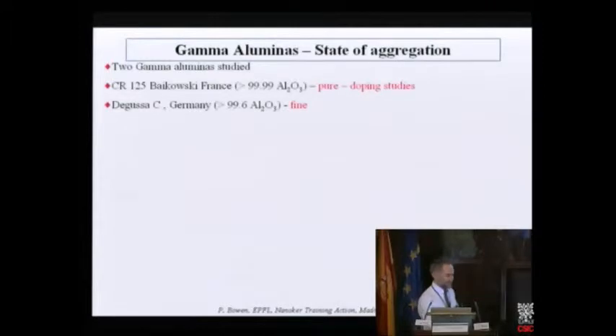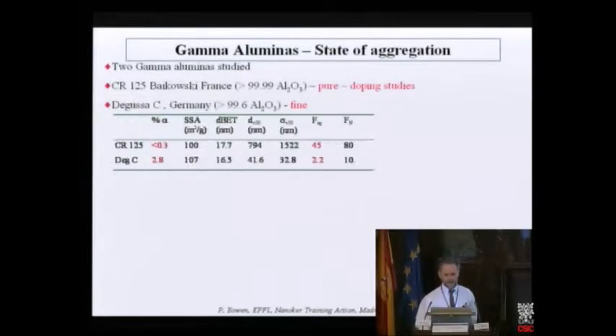We've been working on this for quite a few years. We looked at a couple of gamma aluminas, one from Baikowski, one from Degussa. One is very pure, so it's quite good for doping studies. Less than 10 ppm silicon and calcium, so we don't have this intergranular phase problem. The Degussa C is a little bit less pure. But you can see when we measure the particles, surface areas are high, about 100 square meters per gram. Primary particles are small, about 20 nanometers, but the CR125 has an agglomeration factor of 45. The Degussa C is not too bad, only an agglomeration factor of 2.